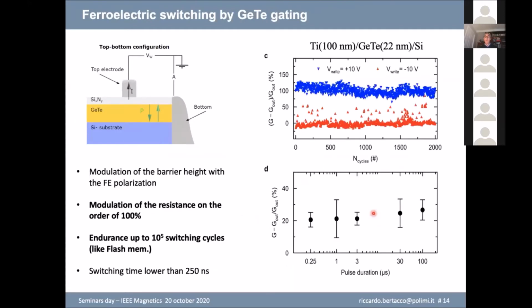Now, just to give you some information about the reliability, it's really reliable because it persists up to 10 to the 5 cycles that you can apply. Here is the percentage variation between the two states up to 2000 cycles. You see that there is no appreciable change in the percentage variation, which means you have two distinct states. And also the writing time is not so high, because it's below 250 nanoseconds, which has been the minimum pulse duration that we used in the last measurement. Probably we can go down.